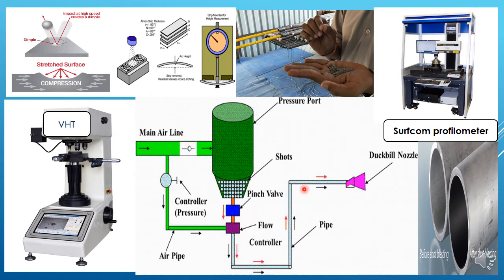So what is the procedure? Let us discuss how we do shot peening in a tube or coils. A coil or sample is laid down on the test bed. There is a 2 mm stainless steel wire with 12 mm steel balls attached at every space of 500 mm, and this wire is inserted from one end of the tube and taken out from the other end by a suction pump. These balls can oscillate to and fro within their fixed space of 500 mm.